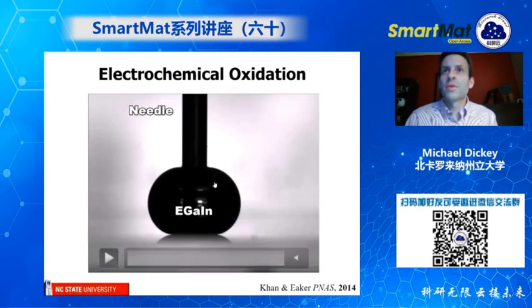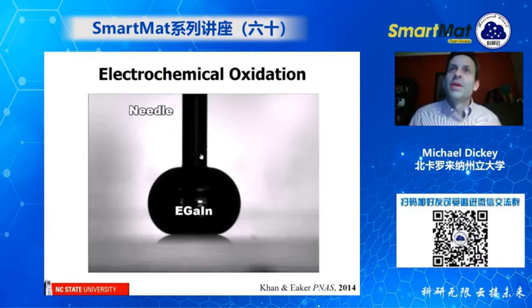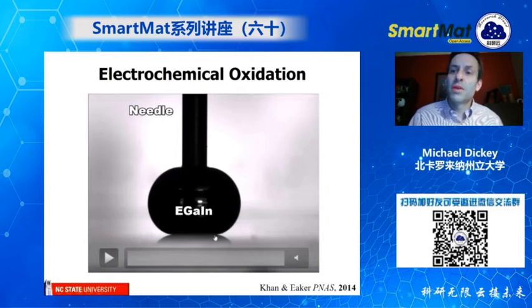So this is a droplet of this liquid metal, eutectic gallium and indium, and it's sitting in sodium hydroxide. Remember what I showed you where it beads up? And you can see that the metal here has very high surface tension. In fact, it's almost a perfect sphere. So we're going to apply a positive voltage. And remember, what you would expect is that the surface should form an oxide and nothing interesting should happen.